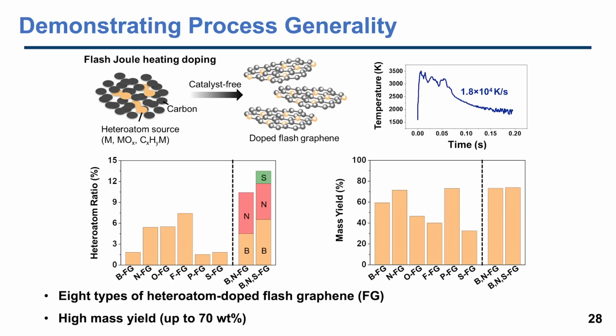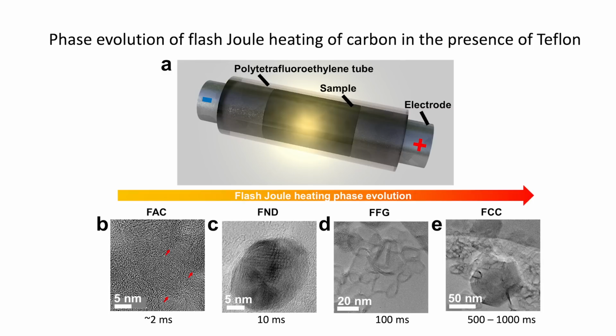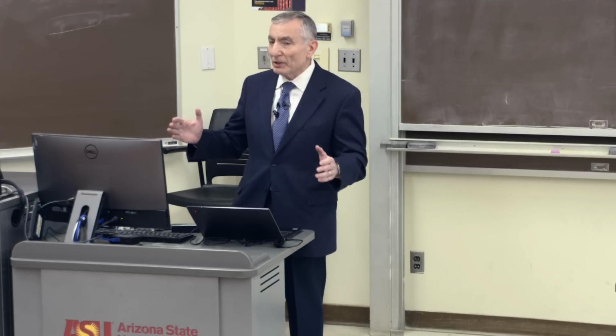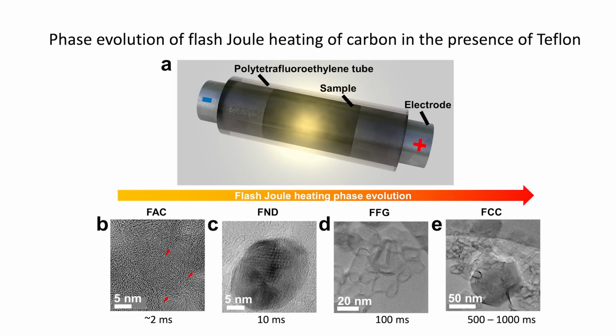You can watch the evolution of this. So this is over 1 second. We think of evolution over periods of hundreds of millions or billions of years. Think about evolution over a period of 1 second. If you take, say, carbon black and you flash it, in the first 2 milliseconds, it's still amorphous. By 10 milliseconds, this was actually a sample of polytetrafluoroethylene, which is Teflon. We're flashing Teflon. In the first 10 milliseconds, it forms into fluorinated nanodiamonds. If you continue heating to 100 milliseconds, you get the fluorinated flash graphene.